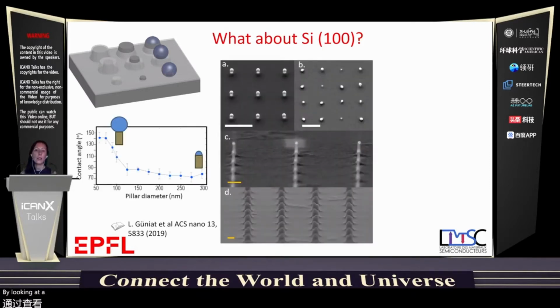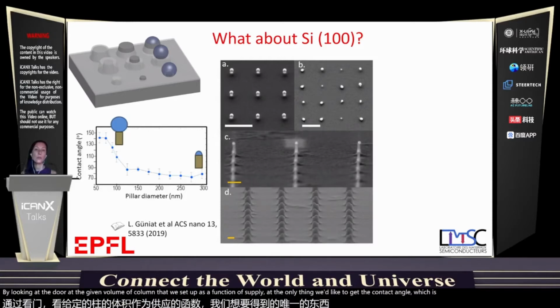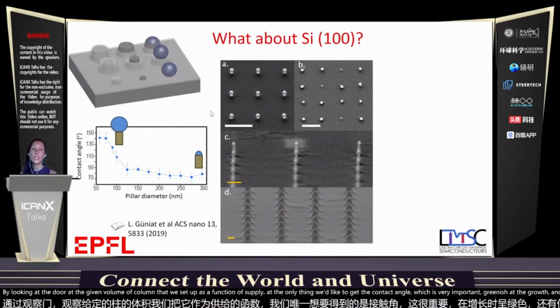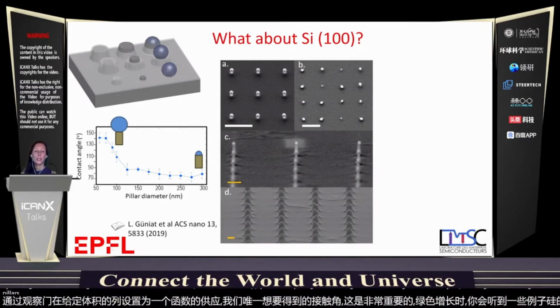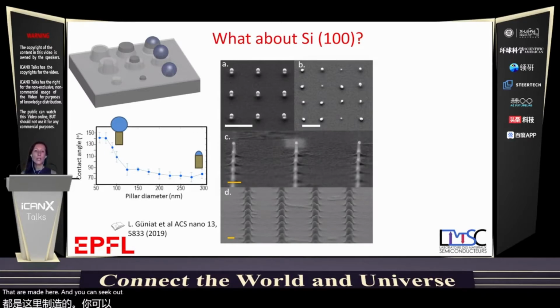To get rid of this shadowing effect, we created pillars that we oxidized and we then deposited the droplets on top. By looking at the given volume of gallium that we sent as a function of the pillar diameter, we could engineer the contact angle, which is very important to initiate the growth. And you here see examples of arrays of gallium droplets on silicon pillars. And you can see how they are very reproducible from one to the other.